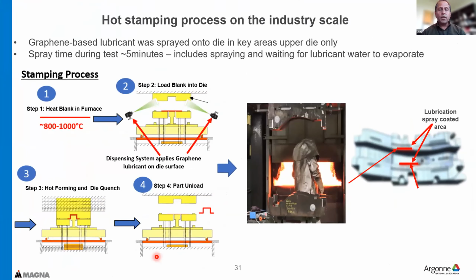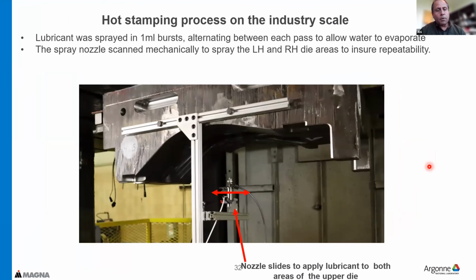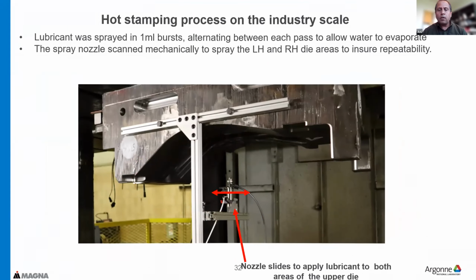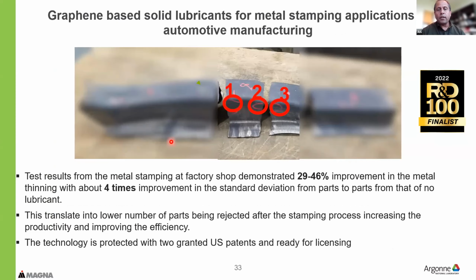Now, going from the lab scale to the industry scale, this process involves heating the blank to 800 to 1000 degrees Celsius, then spray coating here, and then stamping at high temperature. And this is actually the area of the block, and this is blurred intentionally for these industry people. And then this is actually the die, of a very large size, where we developed the spray coating process to coat it evenly everywhere, and then it goes to the stamping process, and this is the final product.